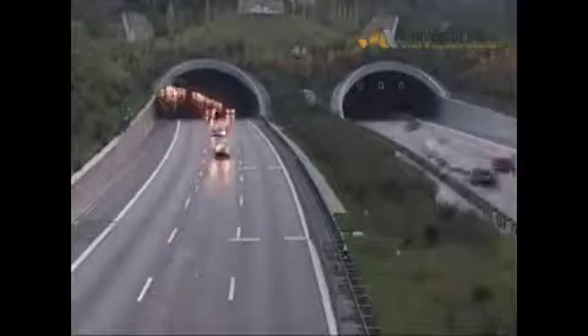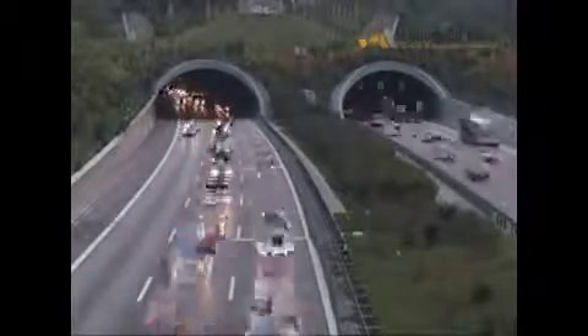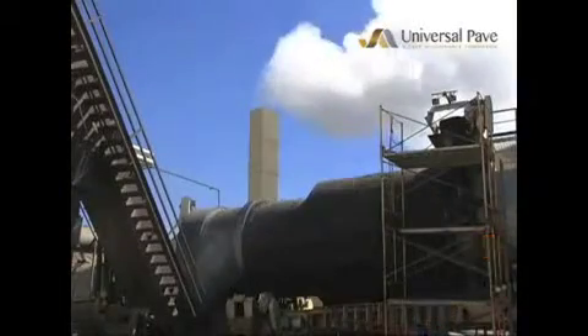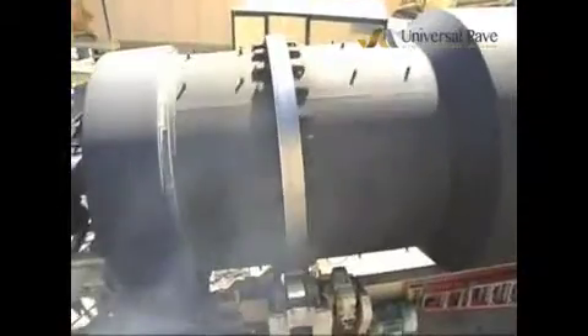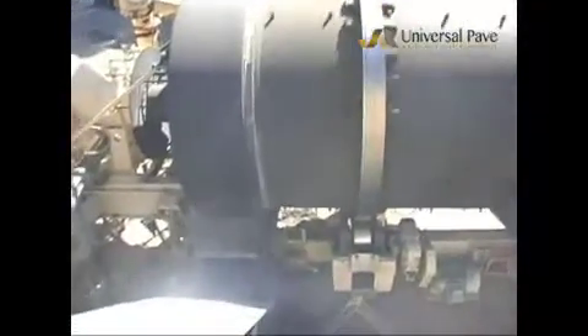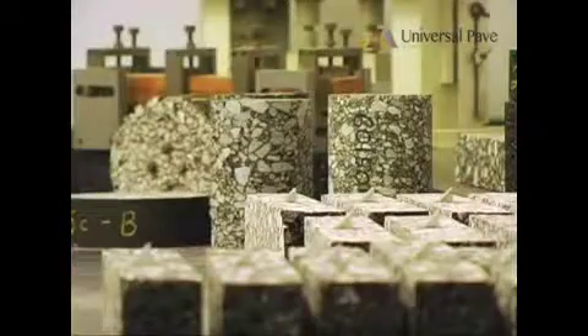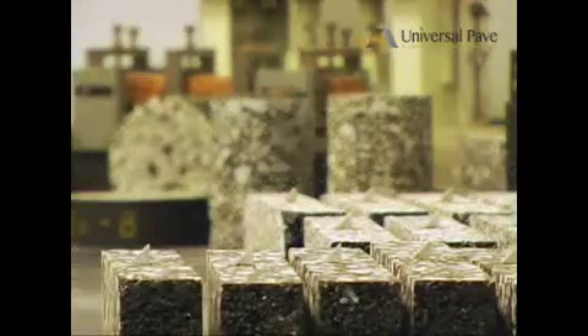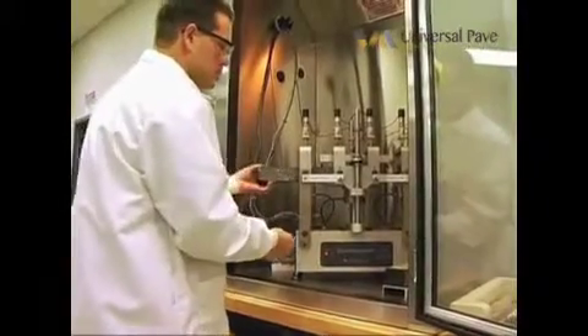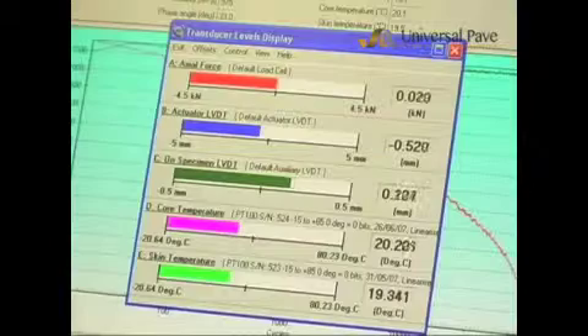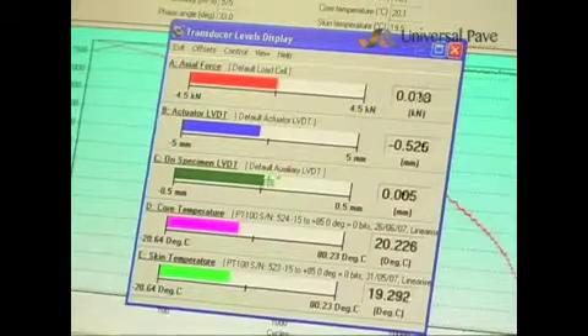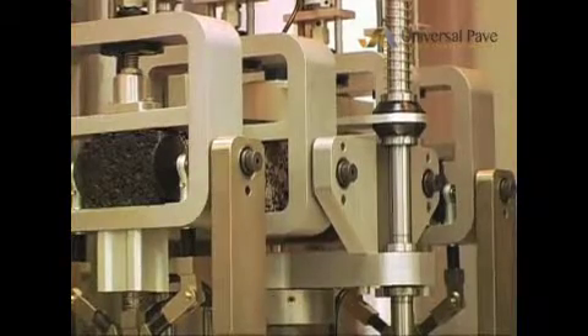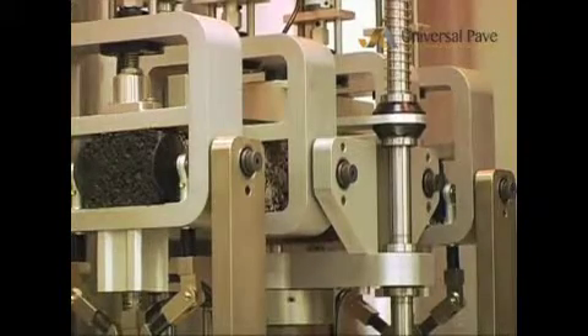One of the reasons the pavements are performing so well may again be tied to turning down the heat. One of the consequences of conventional hot mix asphalt production is that the production operation ages that asphalt an estimated 5 years. So it's really the production temperatures that create the oxidation in hot mix asphalt. And oxidation makes asphalt brittle. In laboratory testing, warm mix asphalt binders that have undergone 7 to 10 years of accelerated aging are exhibiting the same elastic properties of new hot mix asphalt.